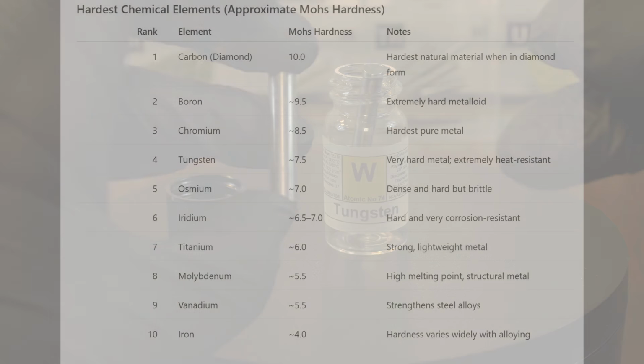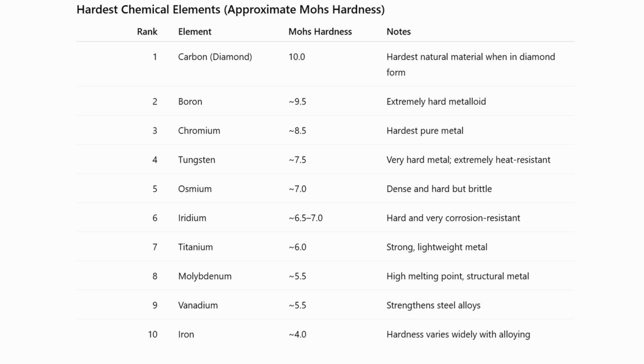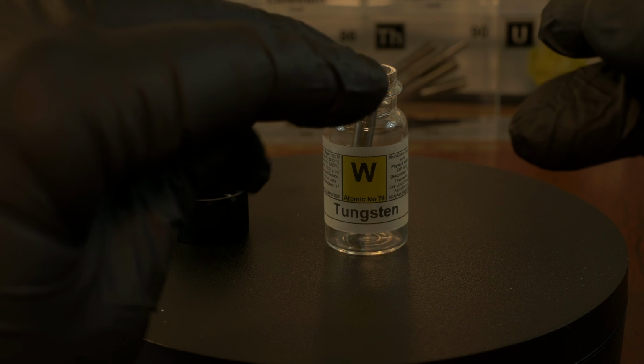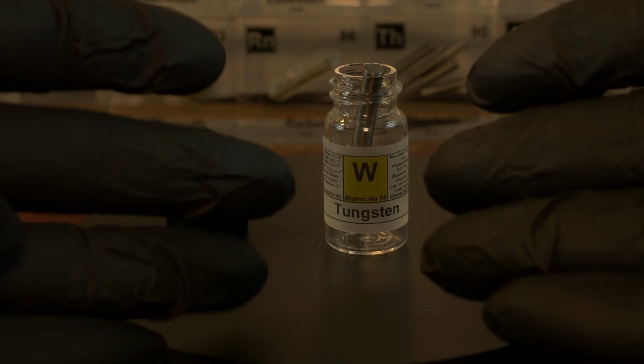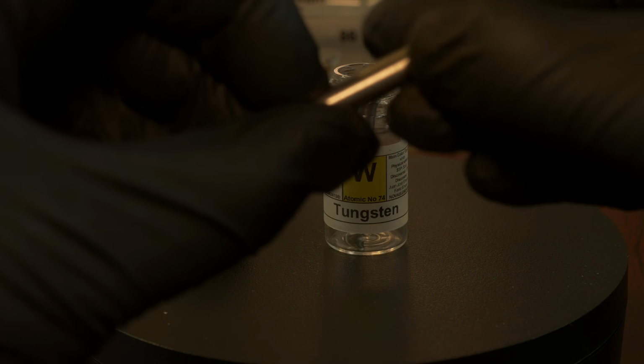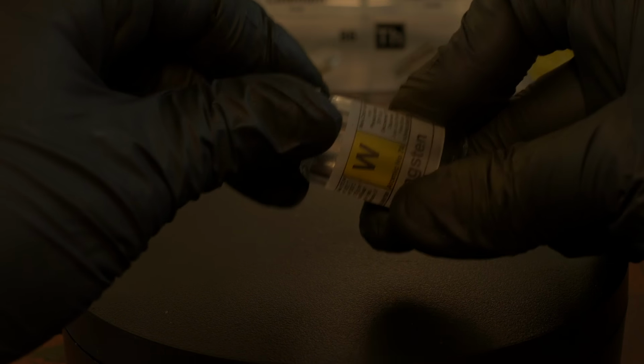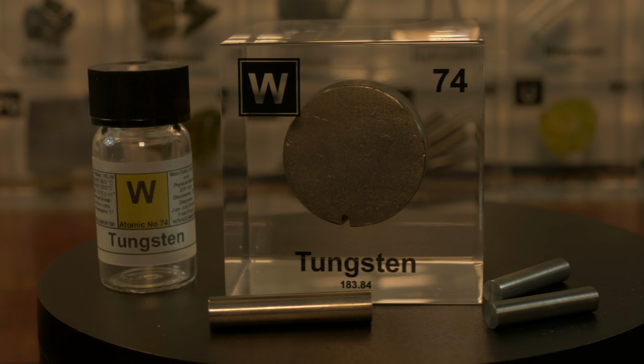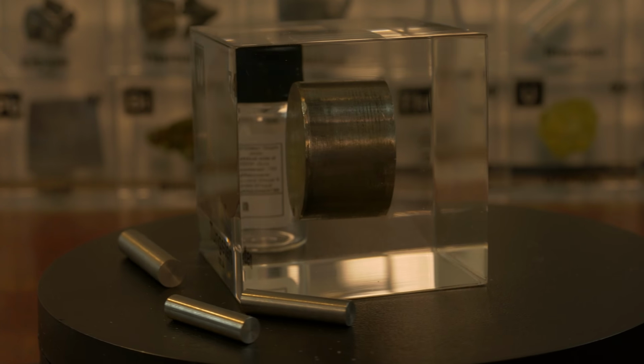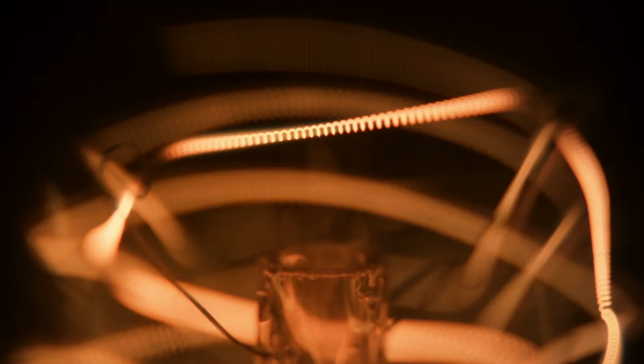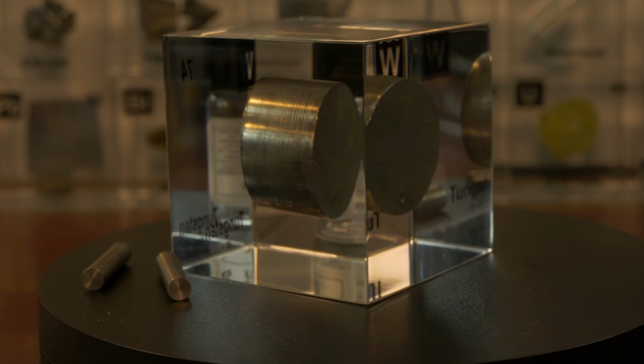Another standout property of tungsten is its hardness. On its own, pure tungsten metal is very hard, harder than many types of steel. In fact, a purified tungsten rod can scratch glass with ease. However, in its common form as a sintered polycrystalline metal, tungsten can be somewhat brittle at room temperature. If you try to bend or hammer a typical tungsten bar, it might crack or shatter rather than deform. This brittleness is because of tungsten's rigid crystalline lattice and the presence of impurities or grain boundaries. Interestingly, if tungsten is ultra purified and made into a single crystal form, it becomes more malleable, able to be bent, while still retaining hardness. Engineers have found that working tungsten at high temperatures or adding small amounts of other metals can improve its toughness. For example, tungsten wire for light bulbs is doped with tiny amounts of potassium and other elements to prevent it from becoming brittle and to keep the filament from sagging when hot.